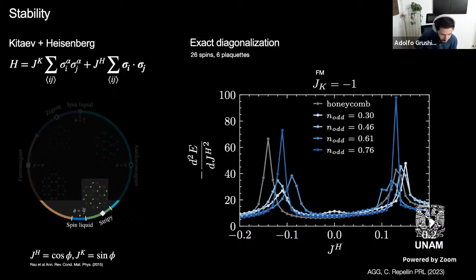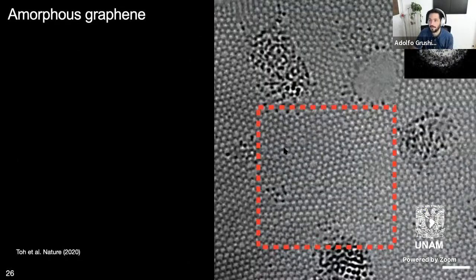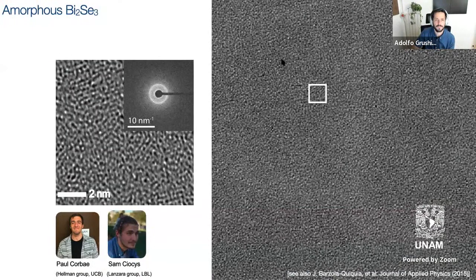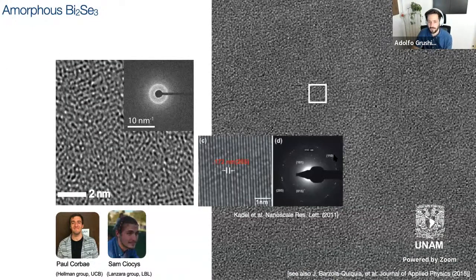Actually, I might be able to show it a little bit for the amorphous graphene. Right here, and maybe even let me see if I have a better one. Yeah, maybe here. Yeah, so you see, a crystal structure has these peaks, right? These Bragg peaks, basically. That's the definition of a crystal. Well, actually, that plus the fact that it has the symmetries that are allowed for a crystal, because quasi-crystals have Bragg peaks, but they have symmetries that are not allowed in a crystal. And amorphous systems, they just show rings. And the rings tell you something about the local distance between atoms.